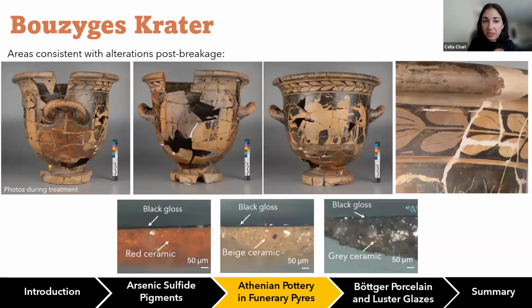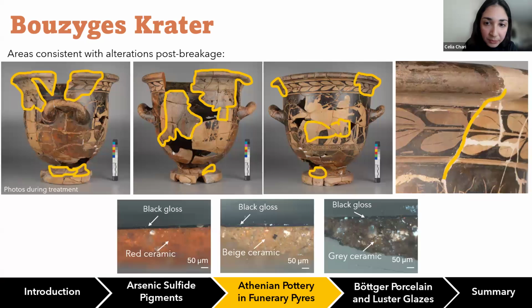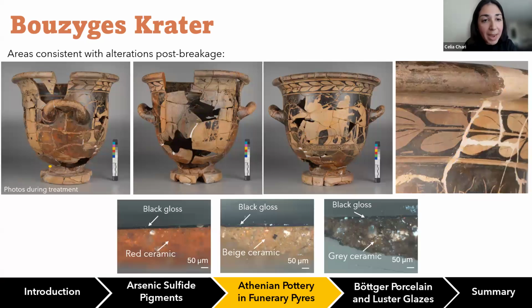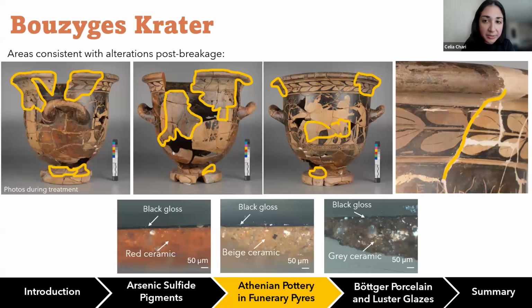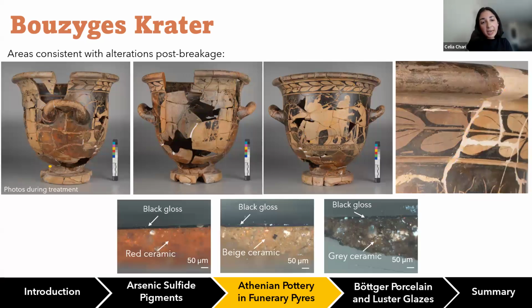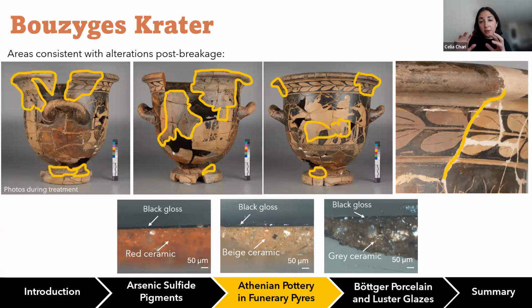On the other hand, there's a different type of degradation that we're observing, and that's shown here. So unlike those red patches, this discoloration of the ceramic turning beige is defined by those break lines. So this is indicating that the change in the ceramic occurred after it broke. And this is where historic context is really important. And working with the curator, Susanna Ebenhaus,